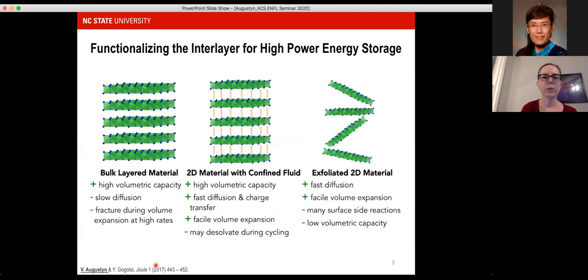And the idea was that the classic intercalation materials, like the ones used in lithium-ion batteries, are micron scale layered materials that exhibit very high volumetric capacities, but can have slow transport processes at high rates. If we're talking about minute time scales, they can undergo fracture if there are phase transformations taking place that don't lead to homogenization of stress. As a field, we've taken materials like this, for example graphite, and exfoliated them to make